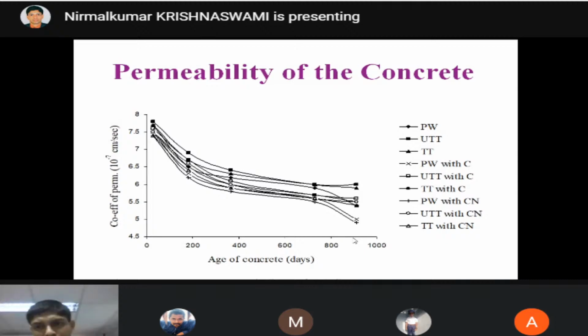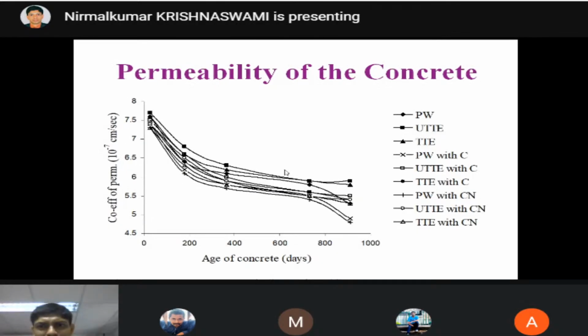Then comes the next durability property, the permeability. Permeability, I hope you know, is the passing of water through the concrete and the time taken, etc. One encouraging factor is that when the years increase, the permeability is getting decreased. So here also it is good. For the tannery effluent, when we add the admixtures, there is not much difference. As we had seen a significant difference in compressive strength or loss of weight due to corrosion, here there is no significant effect. This is for textile effluent and the previous one was for tannery effluent. Here also almost the same property is observed.